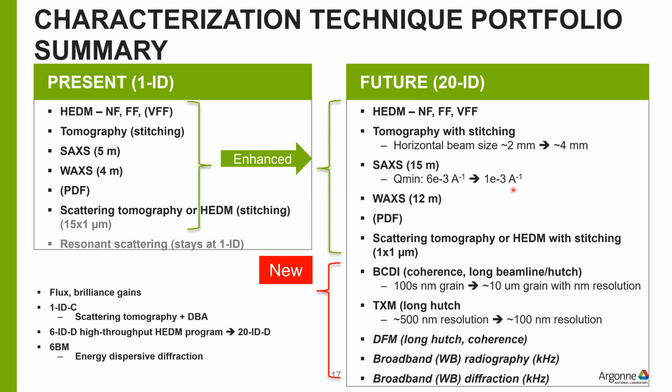inverse angstrom. WAXS, we believe, will be reaching the levels of the high resolution powder diffraction program type of resolution because of the size of our hutch, which I will describe in later slides. And of course, scattering tomography or HEDM with stitching, we believe that we can now attain about 1 micron resolution horizontally because of the improvements in the storage ring, from the current 15 micron resolution horizontally.